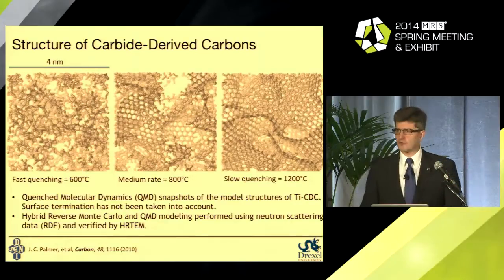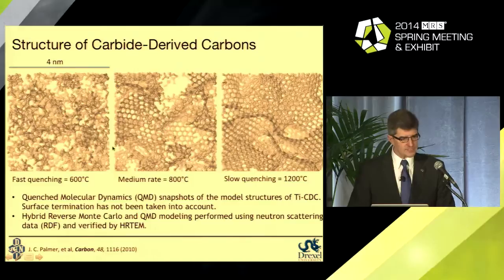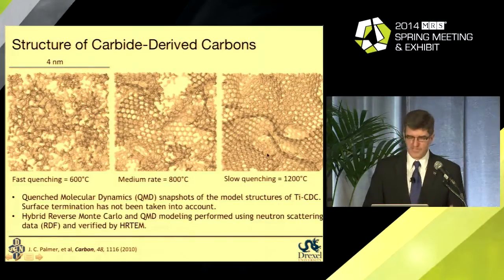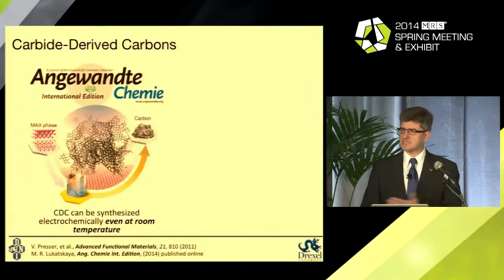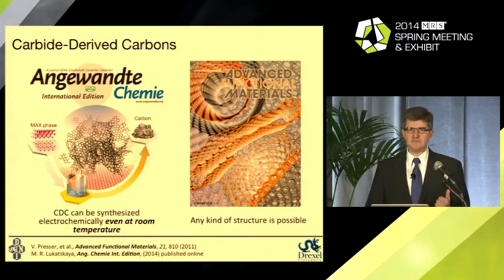Usually we'll get this type of amorphous networks, and they are extremely amorphous even at the highest temperature. However, you will not be able to find any fringes at lower temperatures, and there will be more ordering in the three-dimensional network occurring at high temperatures. So we learn how to make structures. We make, for example, carbide-derived carbon by electrochemical etching even at room temperature. And we can, in general, by extracting metal from carbide, with this simple single technique, produce almost everything from porous carbon networks to graphite, nanotubes, and graphene. This is exactly how many of us make graphene layers on silicon carbide crystals, by removing silicon atoms from the surface of silicon carbide. So we have a variety of methods to make carbon materials here.